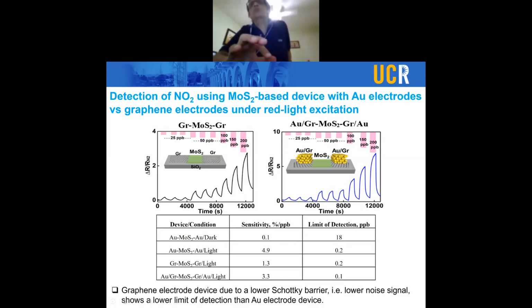The signal to noise ratio in the case of the graphene electrodes compared to just gold electrodes is much, much better. And so the limit of detection, which is defined as signal to noise ratio of 3, is much better for the graphene electrode as opposed to the gold, where the sensitivity is higher, but the limit of detection is slightly worse.